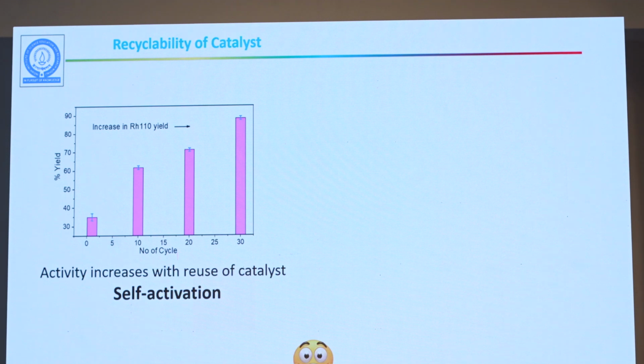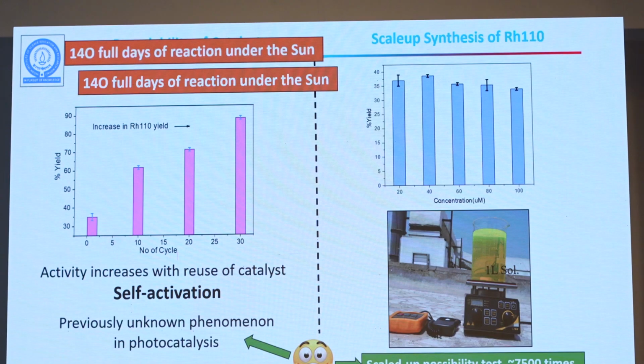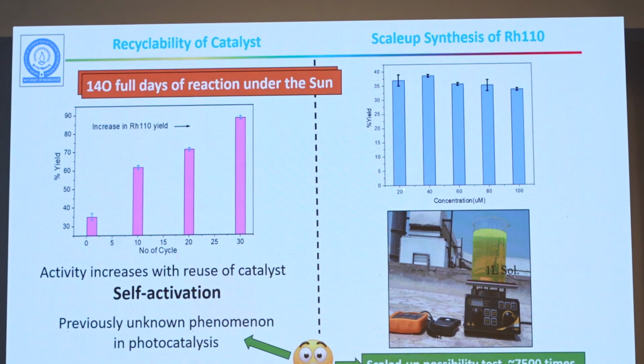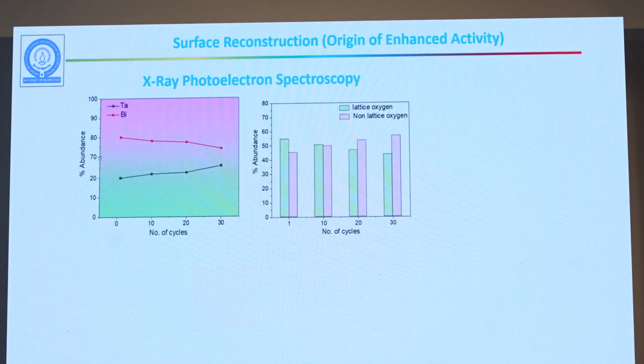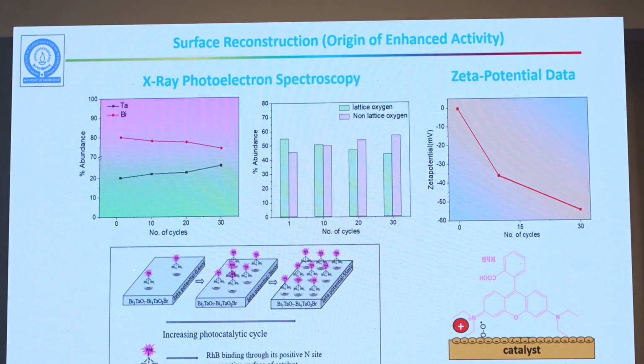The rest, 65%, still becomes CO2. This is on day one. But if you start using it, by the 30th day, you nearly get 100% yield. Everything converts to rhodamine 110. And this is very good. Then we can increase the concentration by 5 times. We can increase the amount of dye that we are using. So if you put all of them together, it is roughly 7,500 times improvement. And we can get solid products which we can separate out. Then I'll come back to this one later. At this point, I wanted to emphasize that this molecule, when you look at it, can sit on a catalyst surface 2 ways.